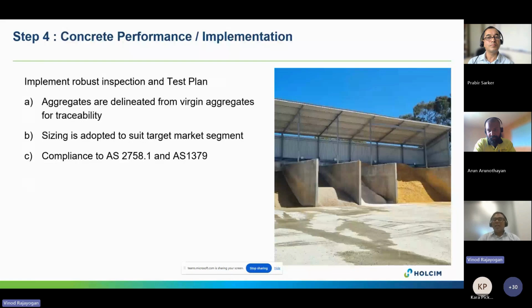Within our concrete plants, space is always scarce, but it was critical for us to delineate from virgin aggregates to allow for traceability. In at least 3 of our plants, we have isolated areas with a designated bin to receive the recycled concrete, made with the right sizing to meet the market segments. In all cases, we've been assessing against the standards AS 2758.1 and 1379.